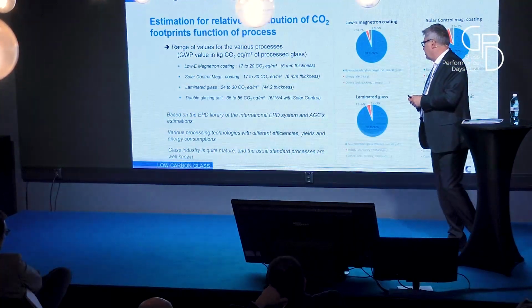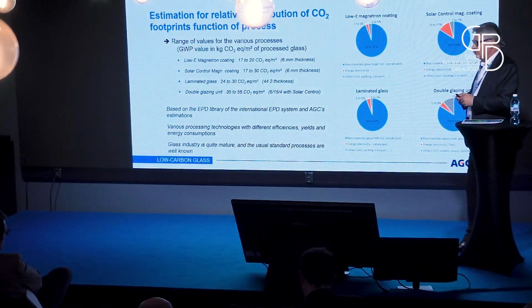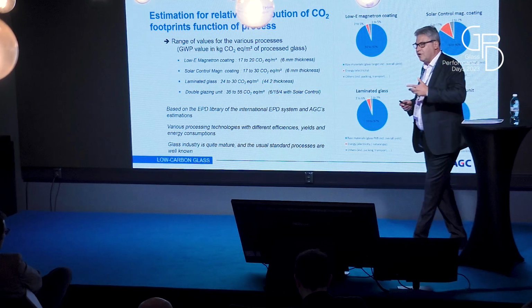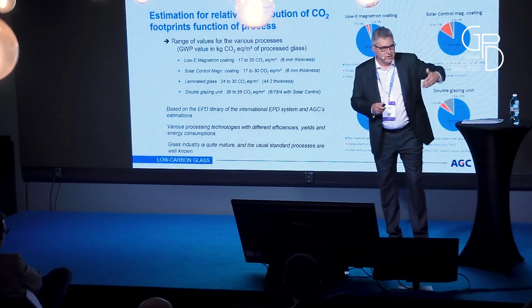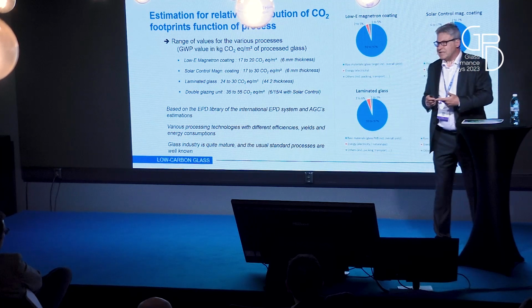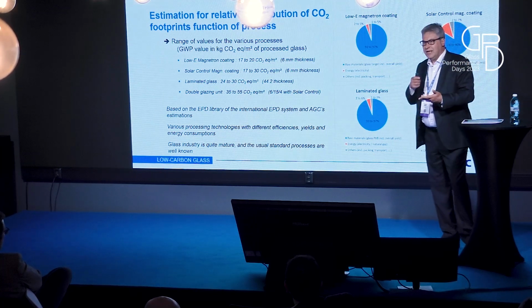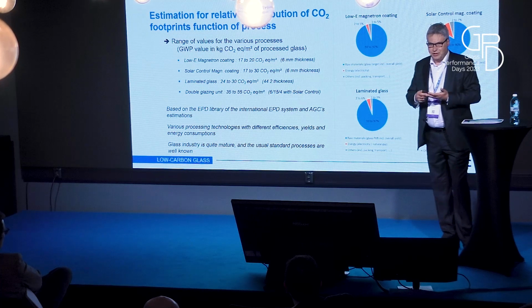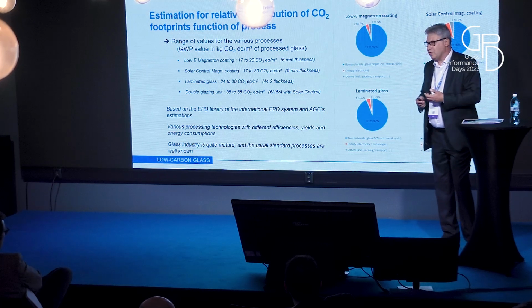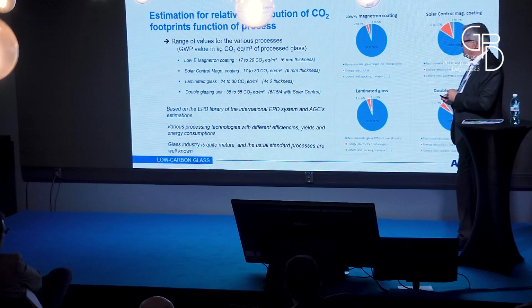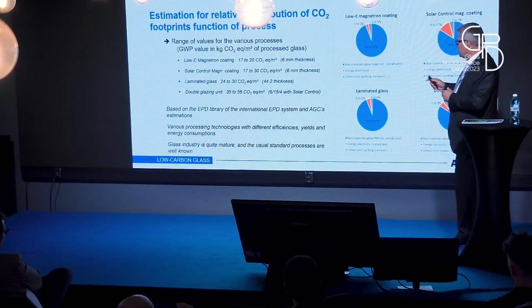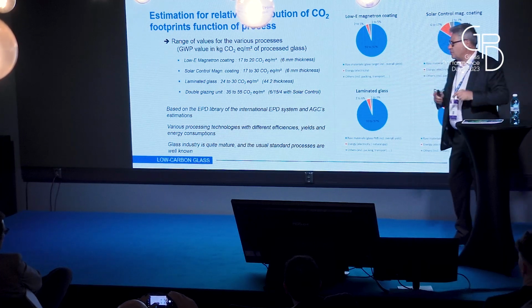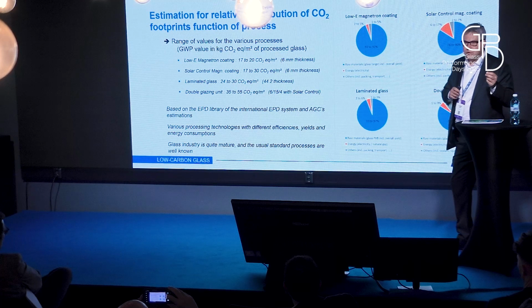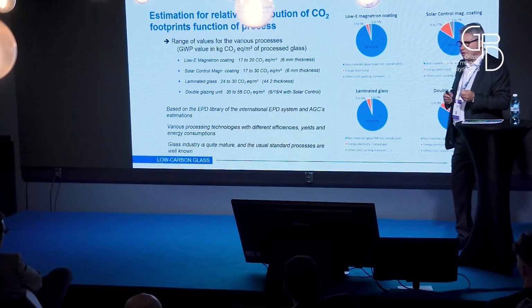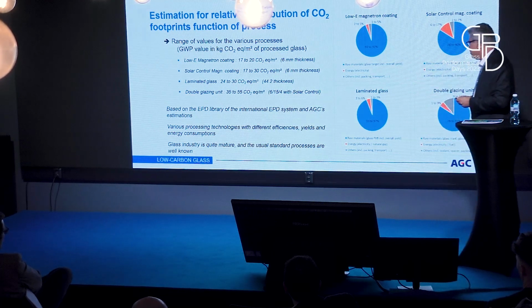So transforming the product, because of course we do not put float on facades, on buildings, on windows, and so on. We put low-E coating, we put solar, we use laminated glass, and finally we also use IGU, double glazing, and so on. So we have a look at all this process. You see different values. It's a range value because there is a lot of difference between a small or large lamination line, a small IGU line or a large lamination one.